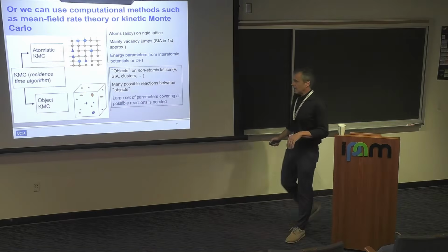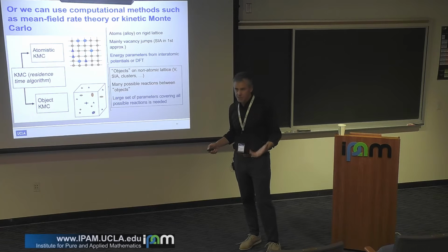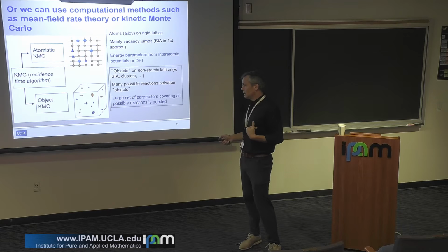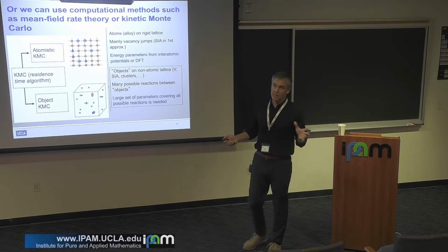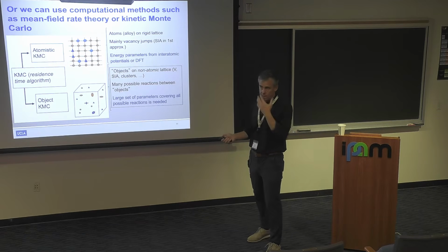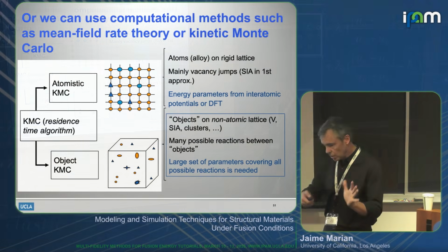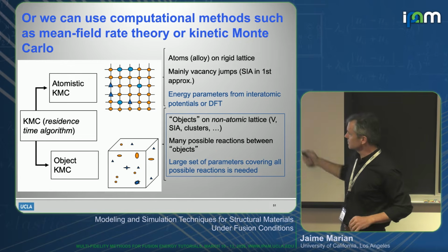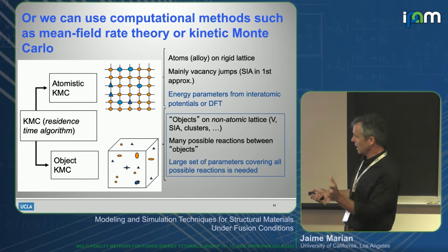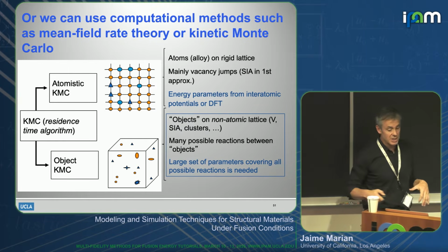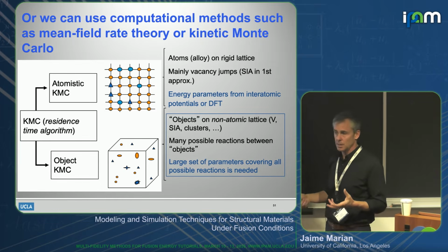Okay, all right, I'm gonna cut to this one. Even molecular dynamics is not efficient enough to push you beyond, let's call it, the microsecond is really pushing it. Really hundreds of nanoseconds and maybe tenths of a micron. Okay, you're still looking at something extremely small. So we can continue up this escalation ladder, this multiscale hierarchy, and we can use Monte Carlo methods, specifically kinetic Monte Carlo methods, in which instead of simulating every atom, now you simulate processes.